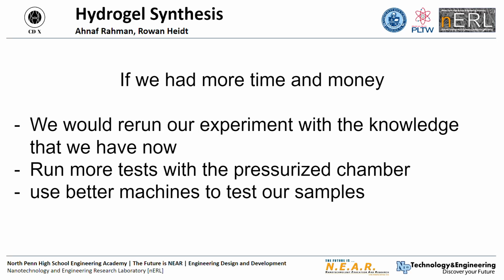If we had more time and money, we would rerun our experiment with the knowledge we know now. We would reorient the bacterial cellulose in the chamber specifically, because that gave us a lot of trouble. We would also run more practice tests with the chamber, as we had quite some difficulty working with it initially. And if we had access to better machines with less limitations, we would use those, as the ones we have here in the high school were pushed to their limits testing our sample.